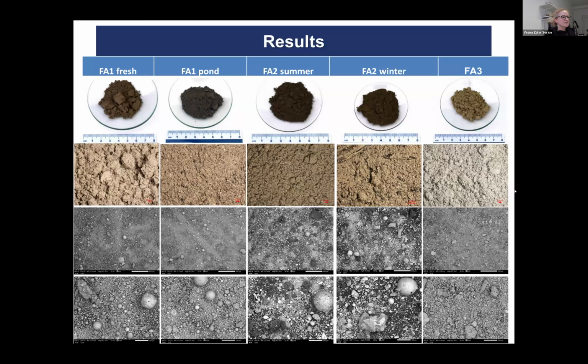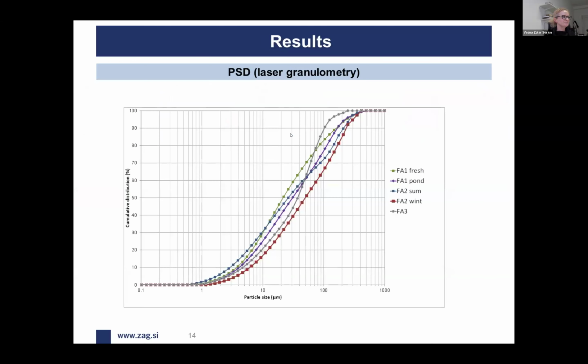So here in the first line, you can see the visualization, and here more deeper insights into their microstructure appearance. There are different colors, of course, because the moisture content is also different. Again, in FA2 samples, it is basically not purely fly ash, but 9% of the bulk volume is composed of the bottom ash, because this is a standard procedure during the collection after the production.